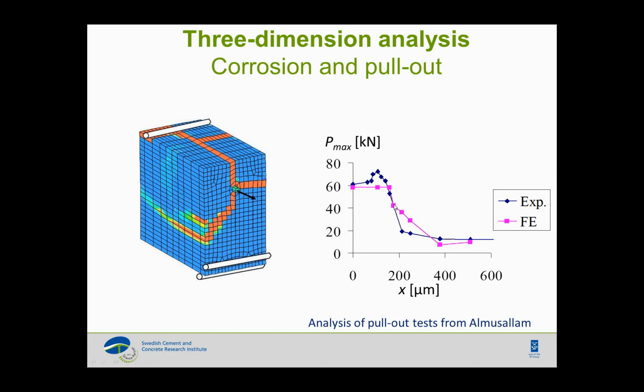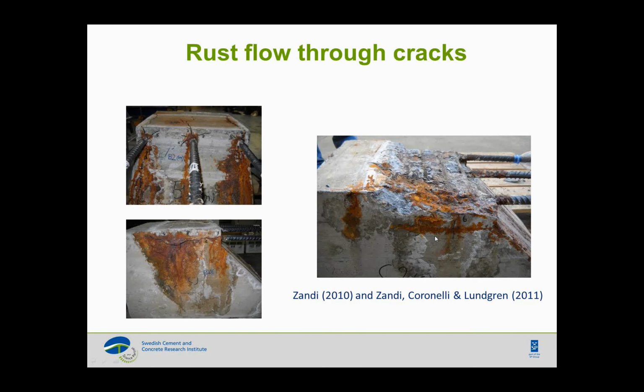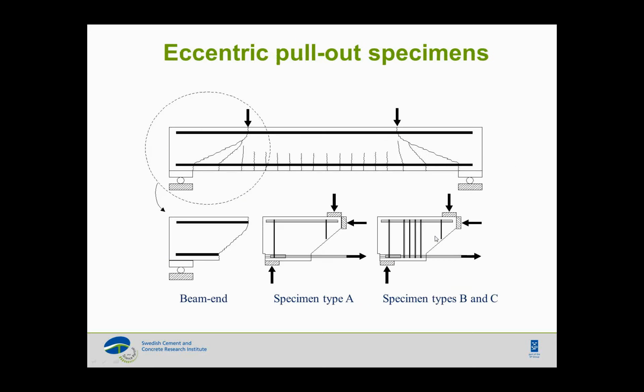Another aspect that we have been trying to implement in our model is the impact of rust flowing through the cracks. What happens is that as soon as the swelling effect of corrosion gets to a level where you have high stresses, you get cracking. That cracking is a release of stresses locally around the cracks, but it also allows the rust to flow out. And this has a good impact, because if you allow the rust to escape from the surroundings of the reinforcement, you build up less pressure. So we wanted to implement that in our model. We did both simulations and experiments for the sake of verification.